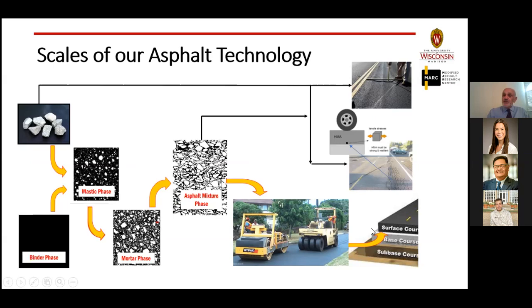The reason I talk about large stresses and strains is here. These distresses, if you will, or failures, are dominated actually by larger strains. If you look at a typical pavement of 4 to 6 inches, and there is about 1.5 or 2 inches of rut, you can immediately recognize that the scale of the deflection indicates the failure is happening at a much, much larger scale than what we use today in testing.